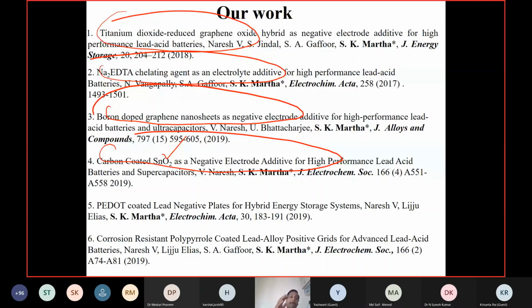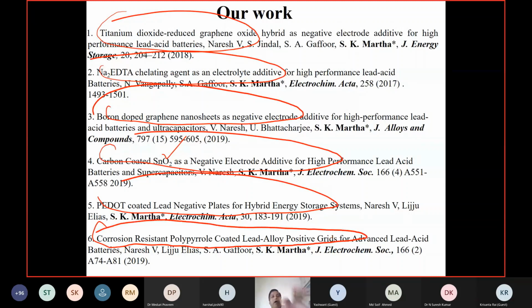So metal oxides, carbon with metal oxide improve the reduction of hydrogen emission and improve the charge acceptance. That's what we have seen actually. Even polymer coating onto the negative plate also improves the performance. So he has also developed a corrosion resistant polypyrrole grid for this, addressing all the issues of lead acid battery.